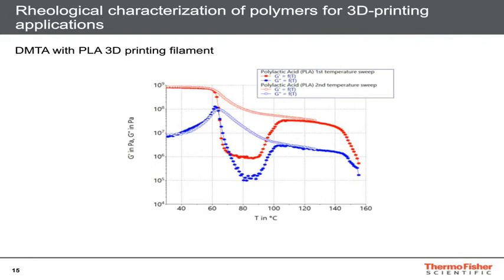On this slide, now we see the results of two DMTA experiments carried out with PLA filament used for 3D printing application. Let's start with the filled symbols. The test was performed over a temperature range from 30 to 160 degrees centigrade. At low temperatures, the material was in its glassy state and showed high values for the storage modulus, G', the red symbols, and the loss modulus, G'', the blue symbols. In this state, G' reached values of around 10 to the 9 Pascal and was about 2 orders of magnitude larger than G''. Up to a temperature of around 60 degrees centigrade, G' remained nearly constant, while G'' was increasing continuously. At 65 degrees centigrade, G'' reached the maximum, which can be considered as a measure for the glass transition temperature of this material. With a further increasing temperature, both moduli dropped almost 3 orders of magnitude into a rubber elastic plateau.